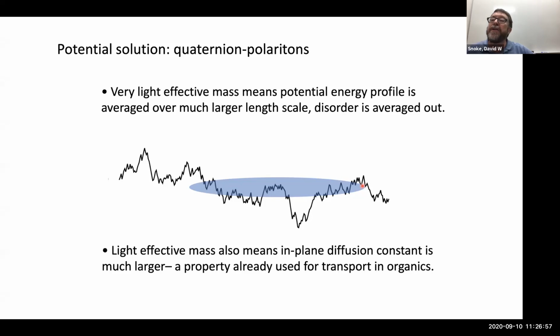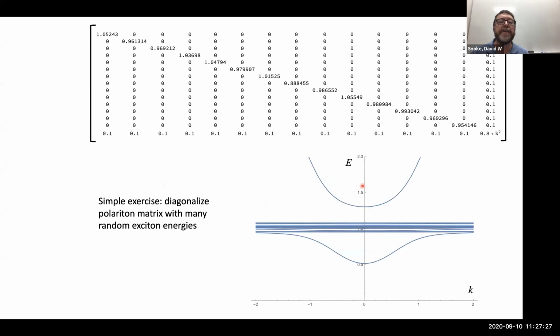The light mass also means that they have a much better diffusion constant, because the diffusion constant depends on the mass. This is already being used. People are making polaritons with excitons in organics to enhance the diffusion in organics. That is becoming a cottage industry in the chemistry field, because organics usually have terrible transport via diffusion of excitons, but the polariton can really enhance the diffusion. I'm going to skip this for the sake of time.